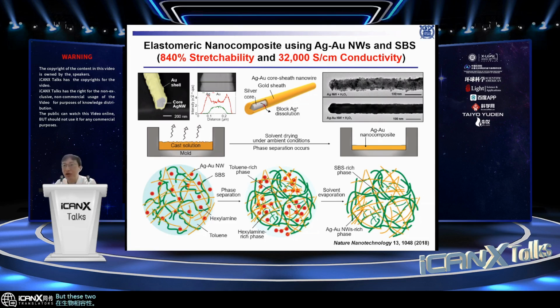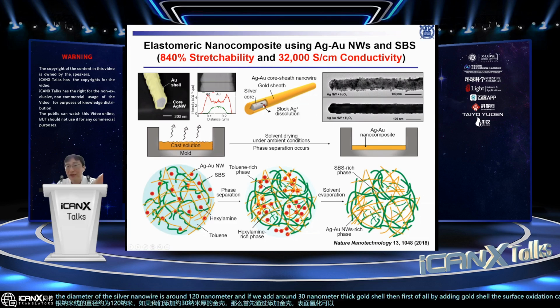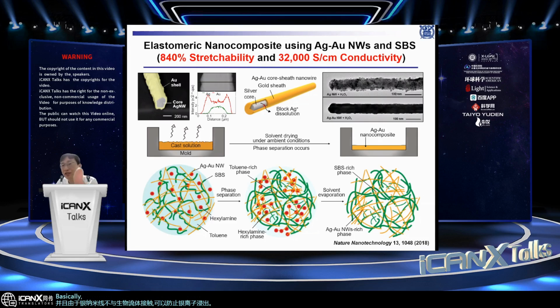But these two issues, the oxidation issue and the silver ion leaching issue, can be solved, can be prevented by using a gold shell. So this is the cross-sectional data. The diameter of the silver nanowire is around 120 nanometers. And if we add around a 30 nanometer thick gold shell, then first of all, by adding the gold shell, the surface oxidation can be prevented. And since the silver nanowire is not contacted with the biofluid, silver ion leaching can be prevented. So basically, the oxidation resistance as well as the biocompatibility can be achieved.